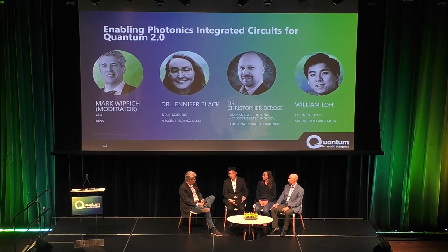One is narrow linewidth lasers on chip. It sounds easy. Lots of people are in it. But as you scale bulky systems down, especially when you get on chip and into waveguide material, the refractive index just changes from anything. A window passes by, the refractive index has changed so that your laser shifted about 1 gigahertz. Now, if you're trying to target an optical atomic clock where your transition is on the level of hertz, you need like nano-Kelvin stability. So that's been very challenging. We have the narrowest linewidth laser in the world on chip right now, but even then, that's just barely able to address this.